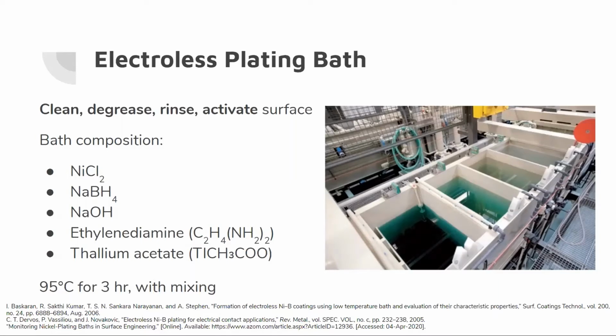So after this, we put the component into the bath, which is made of the following chemicals. We have nickel chloride as the source of nickel. We have sodium borohydride as the reducing agent. This is to help with the actual process of depositing the ions onto the surface. We have sodium hydroxide to make the bath alkaline. And we have ethylene diamine and thallium acetate as the complexing agent and the stabilizer to make sure that the process is effective. We place these components into the bath for 3 hours at 95 degrees Celsius, and we ensure that there is consistent mixing to make sure that all surfaces are reached with these chemicals.